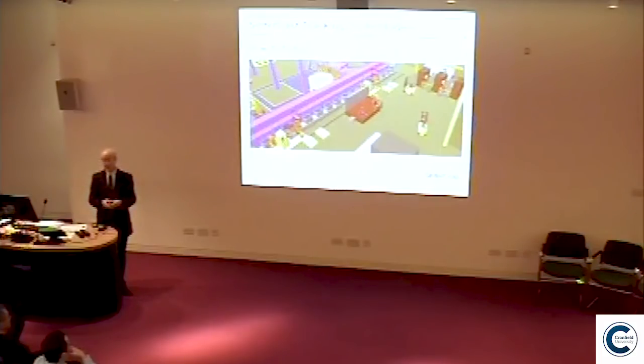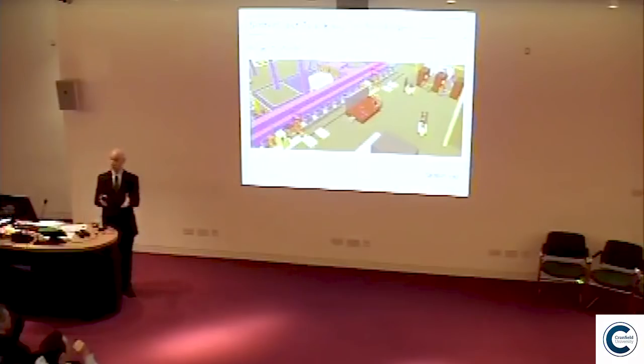It's a really high-volume production — 10 hours per day on the CGI jobs. As we were ramping up initial production, it became clear to everyone — to the foundry, to us, and to the end user, which was Ford — that both engine blocks are for Ford, and that the operators would get it muddled. It's just too demanding. So the idea was: when we base-treat a ladle, we take the Sintercast sample, and we say this ladle needs five metres of magnesium wire and eight metres of inoculant wire. Each ladle has its own recipe. We developed a system where when the ladle arrives at a station, it says, I'm ladle A — I need five metres of magnesium. And we automate that.